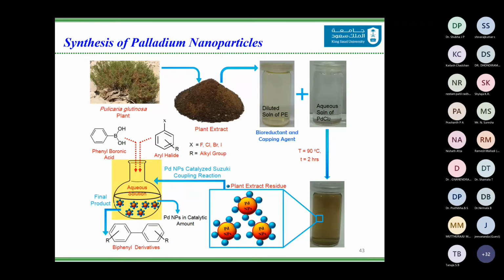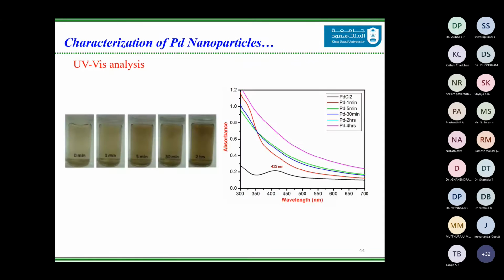So just in brief, I will explain to you how we were able to conclude. So 415 nanometers is the range where you will see the signals, the UV max from palladium chloride. So in order to confirm the reduction of Pd+2 to Pd0, this peak has to disappear.